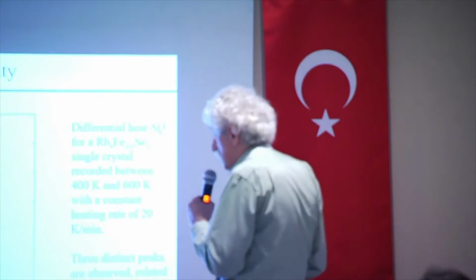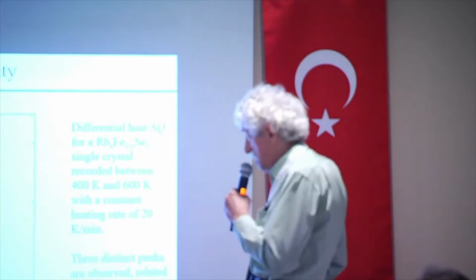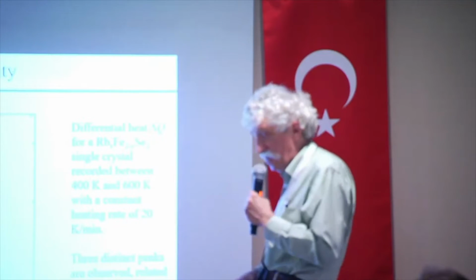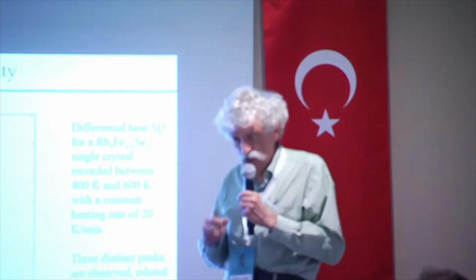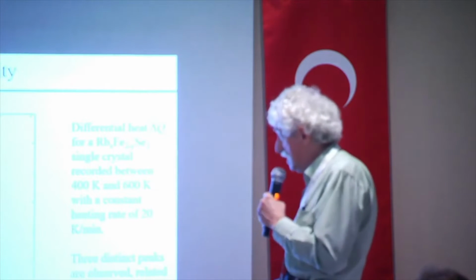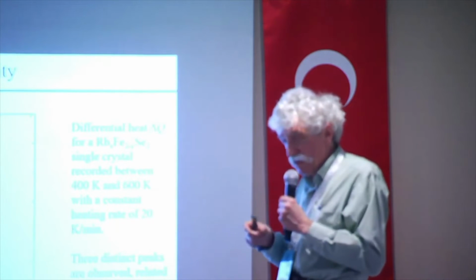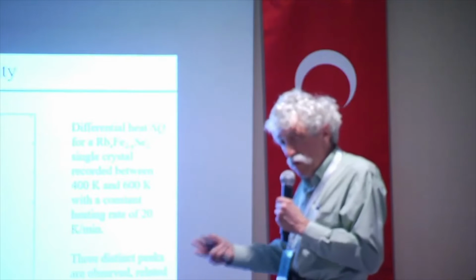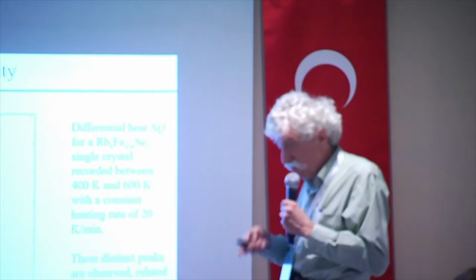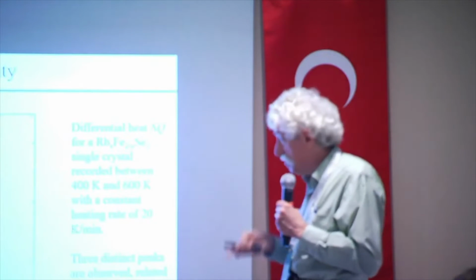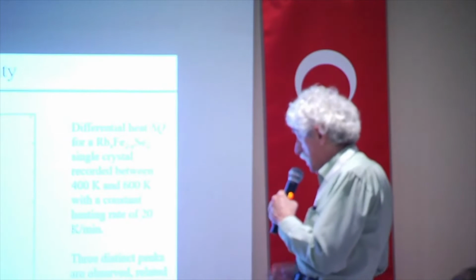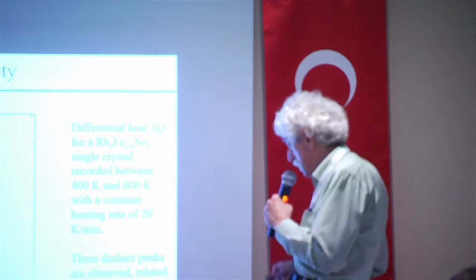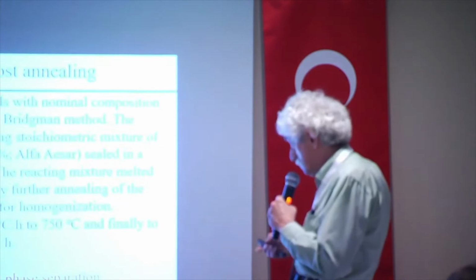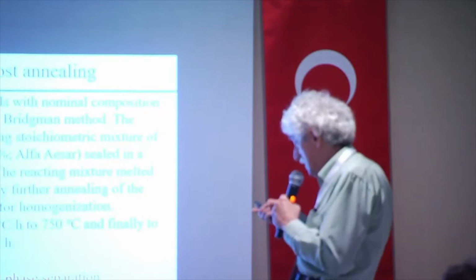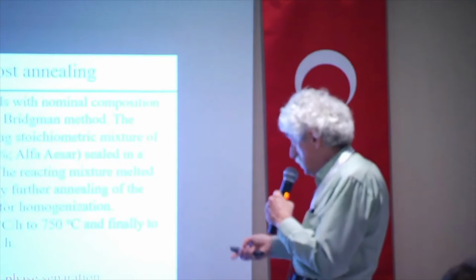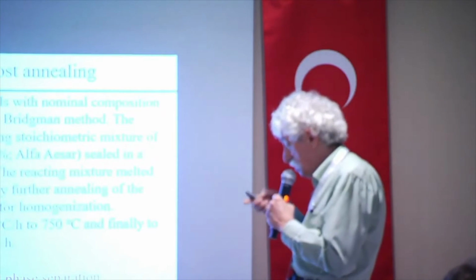in this region. So the idea was to anneal this sample at the phase transition temperature, the same crystal which was grown, and try to check the amount of phases, from one phase to another phase, and check if any change of superconducting properties would be observed. Here is just a description of what was done, but it's also not really important. This is just annealing at phase transition temperature.